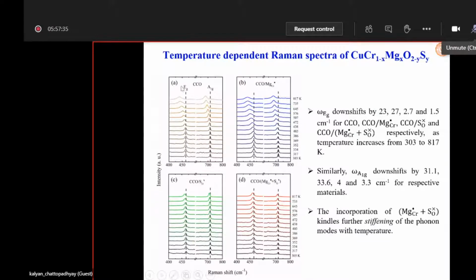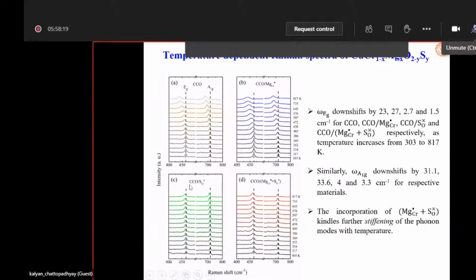Also, as soon as we introduce some magnesium at the chromium site, you see that this shift is also increasing. I have the values of this shift, but you can find the details in the paper about how many inverse centimeters it has really shifted. I just mention the main features of the result without going into that detail because not much time is there. And also, interestingly, as soon as we introduce doping at the anionic site, sulfur at the oxygen site, then instead of phonon softening, phonon stiffening is taking place. So you see here that the peaks are trying to regain their original position. And this effect increases when both anionic site and cationic site doping are simultaneously present.